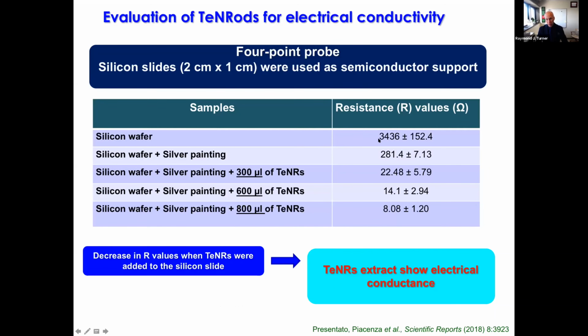Here we just did a resistance test of adding the nanorods to a wafer and measuring the resistance. And you can see as we add the rods, we get decreased resistance. So we have very good conductivity.